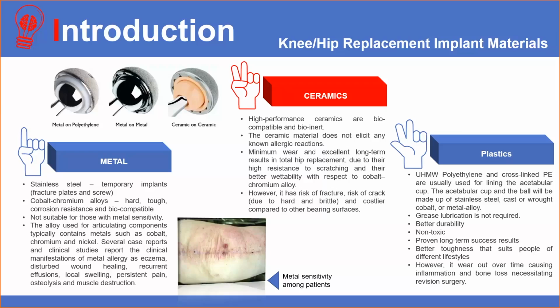Okay, for metal, stainless steel is normally more suited to being used as a temporary implant, such as fracture plates and screws, due to its limited ability to withstand corrosion in the human body. However, one area of concern when using metal is the release of metal ions, such as nickel, into the bloodstream that would subsequently lead to many health issues, including kidney disease and neurological damage, especially for those with a metal allergy. So compared to metal, ceramic implants seem to be promising for patients with allergies against metallic implant materials.